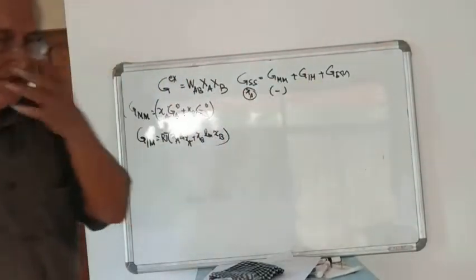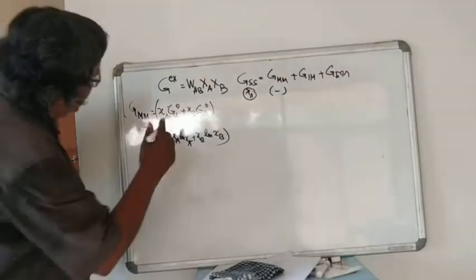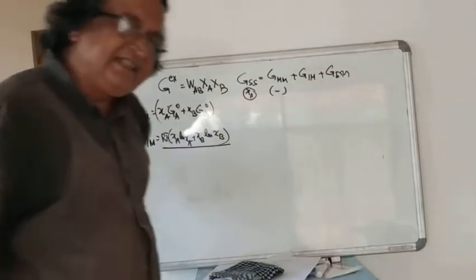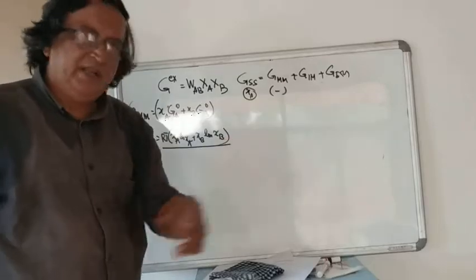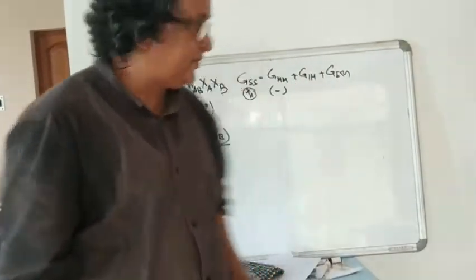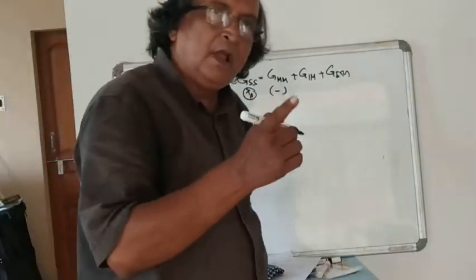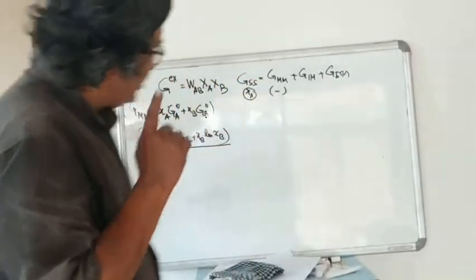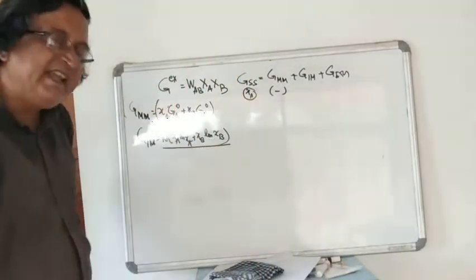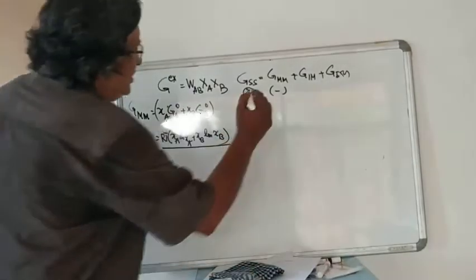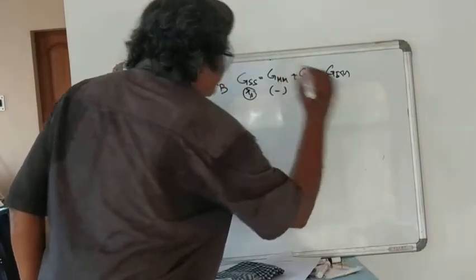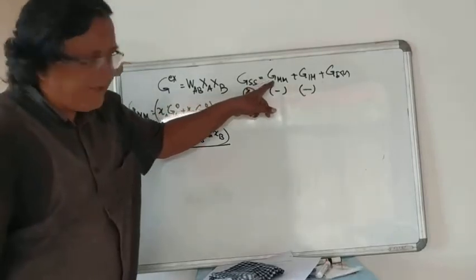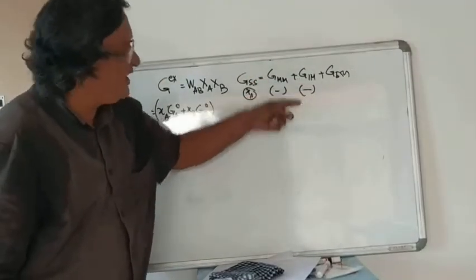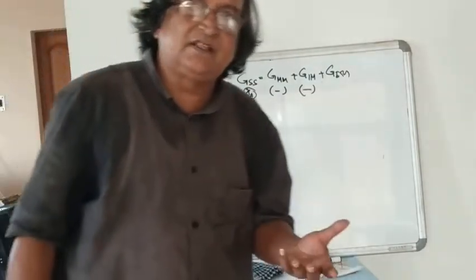Now, if you look at ideal mixing, then this is the term. And you are a solid solution, not XA equal to 1, that means pure A, or XB equal to 1, which is pure B. Not like that. In the intermediate range of composition, XA and XB are both decimals. So if this is so, then ln of a decimal is negative. So this term is negative. So this is negative for the mechanical mixture, and as we discussed before, G ideal mixing makes it more negative. So an ideal solid solution is more stable than a mechanical mixture.